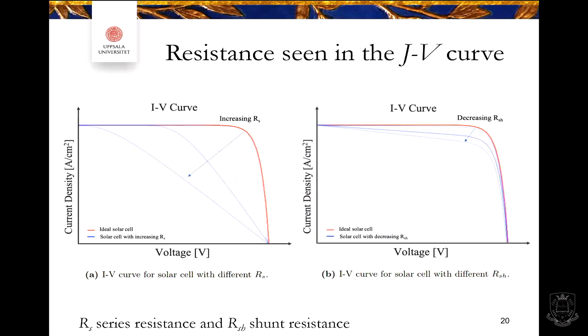We want to have as low serial resistance as possible, but as high shunt resistance as possible, to have as good a functional solar cell as possible. Because if the shunt resistance is low, it means that current is sneaking around the layers. It doesn't go through the layers. Maybe there is a hole in one layer, and then you have some current that goes through those. So it's connected to the efficiency of the solar cell as well.